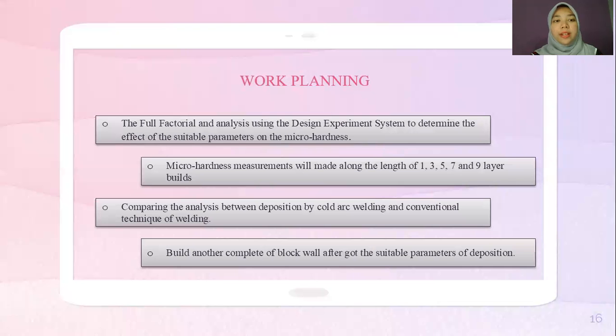This is the work planning. The full factorial and analysis using the design of experiment system to determine the effect of the suitable parameter on the microhardness. Microhardness measurement will be made along the length of layer 1, 3, 5, 7, and 9 of the layer build. Comparing the analysis between deposition by cold arc welding and conventional technique of welding, and building another complete block wall after getting the suitable parameter of deposition.